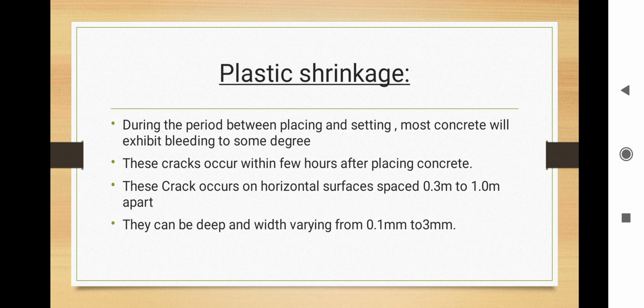Usually the bleed water evaporates slowly from the concrete surface. If environmental conditions make the evaporation faster than the water being supplied to the surface by bleeding, high tensile stresses can develop. These stresses can lead to the development of cracks on the concrete surface. Generally, these plastic shrinkage cracks are wide as well as deep. These cracks occur on the horizontal surface. The crack spacing is 0.3 meter to 1.0 meter apart, with a width varying from 0.1 to 3 mm.